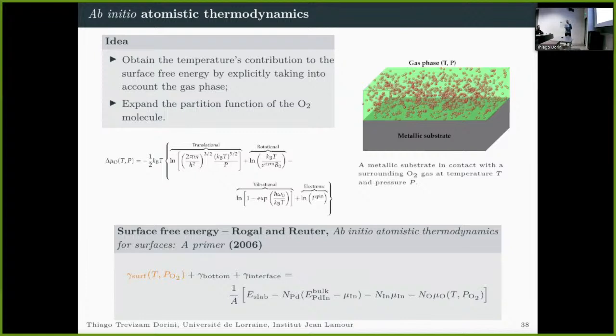And by using the methodology that was proposed by Reuter and Scheffler in their famous paper and applied to our system, we have this equation to calculate the surface free energy of our structure. And we can have the temperature and pressure contribution by expanding the chemical potential of the oxygen molecule, the O2 molecule.